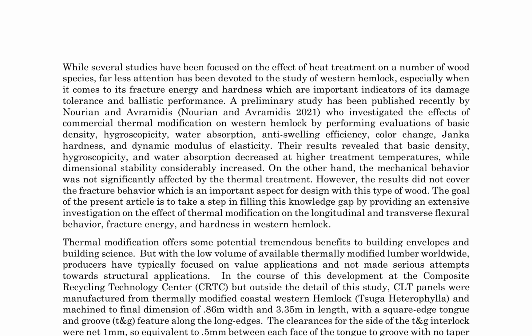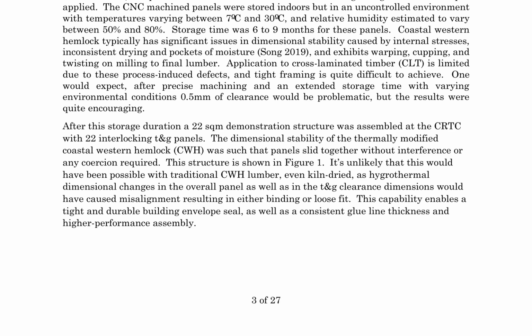Although their results showed decreased basic density, hygroscopicity, and water absorption, as well as increased dimensional stability, thermal treatment had no significant effect on mechanical behavior. Notably, this study did not investigate fracture behavior, a critical aspect for design with this type of wood. This knowledge gap is addressed in the present study, which provides an in-depth investigation of the impact of thermal modification on longitudinal and transverse flexural behavior, fracture energy, and hardness in Western hemlock.